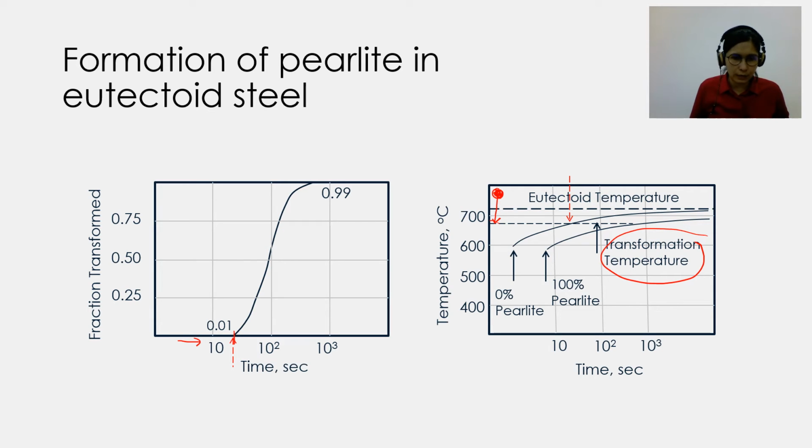So after 40 seconds, even without looking at the microstructure, we know that the first pearlite colony will start to transform from austenite. And we can predict that this transformation will end after around, let's say, 800 seconds here. So this is how we can use the TTT diagram to conduct our heat treatment process.